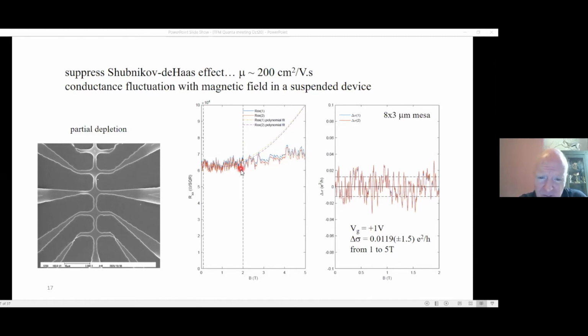These are both sides of the sample. There's a slight change in characteristic here as we change the sweep rate of the field, but irrespective of the field range that we've used, if we calculate this change in conductivity, so conductance variation, it doesn't depend on the region of field that we choose for this conductance fluctuation. What I've done is I've plotted the conductance fluctuation here for both sides of the sample. They completely agree.